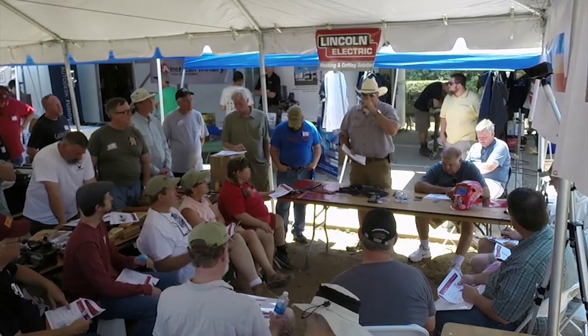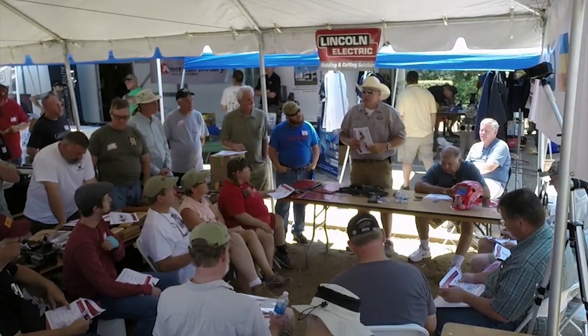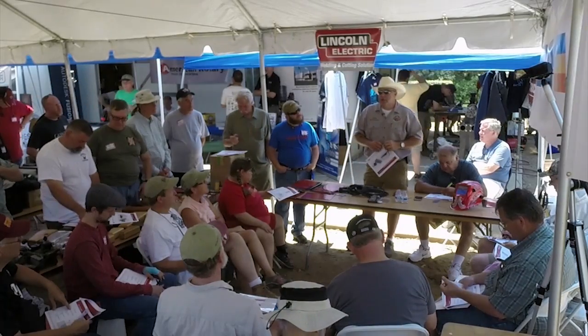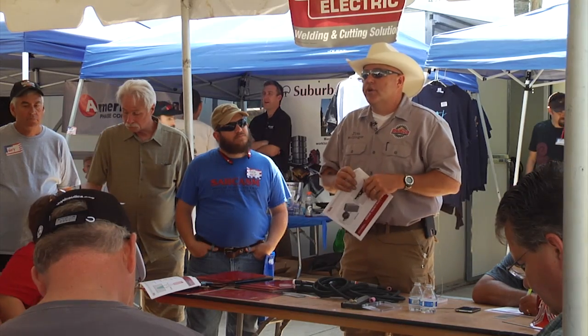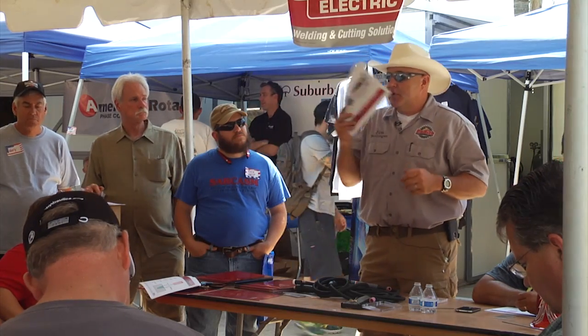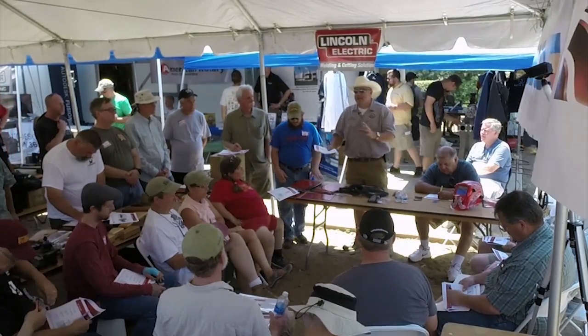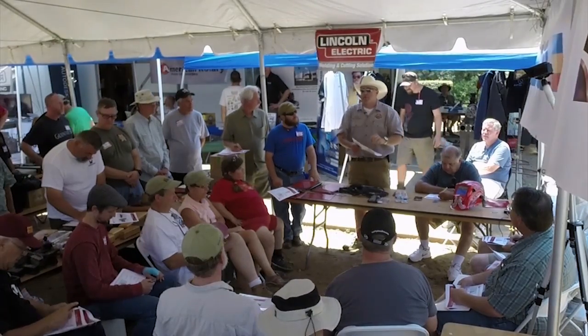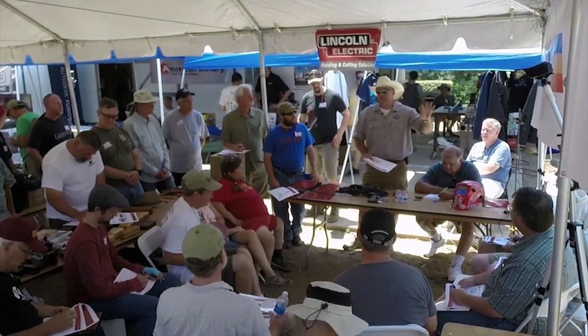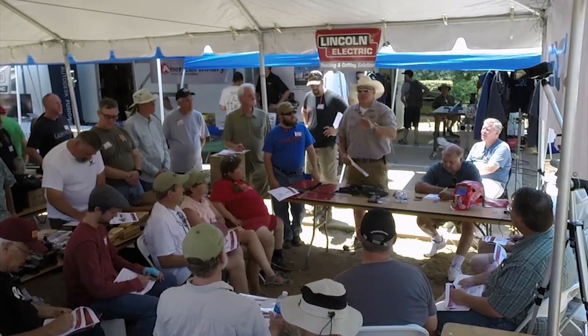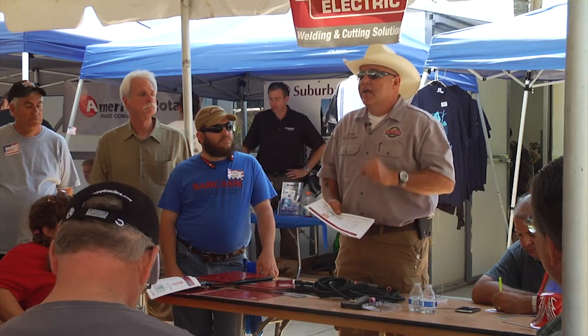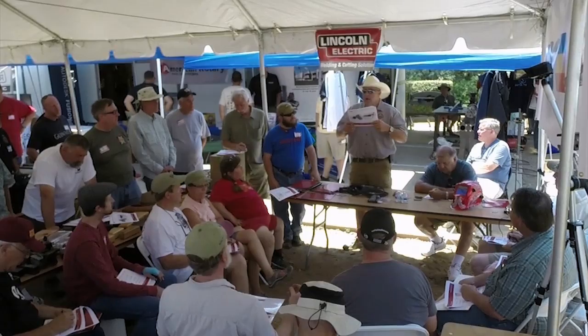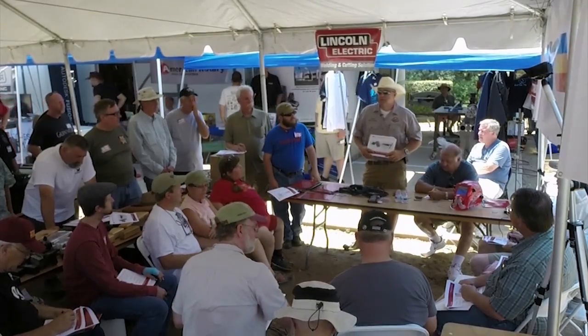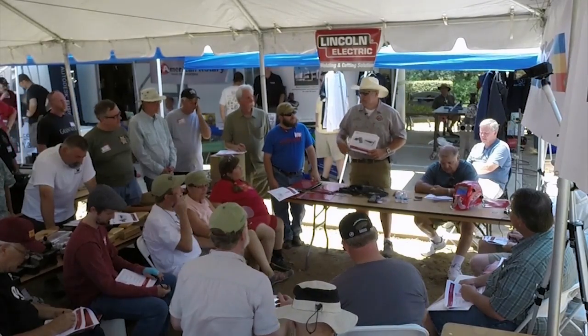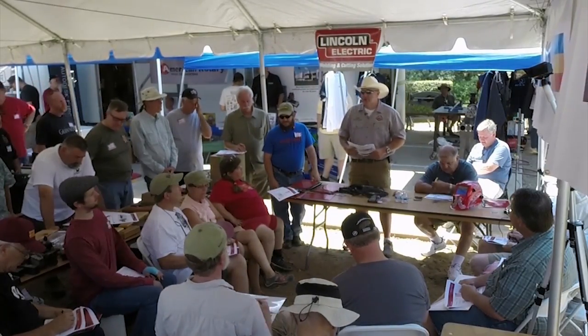Now, those of you that have pens and are taking notes, write this down. 6,280 degrees. At 6,280 degrees, tungsten melts, pure tungsten. I'm gonna tell you, for the sake of easy math, trust me, don't try to look it up on Google, because the decimal points are gonna mess you all up. The arc measured at the center is around 10,000 degrees. So if you have a 10,000 degree arc and 70% of the heat, how hot is the plate? 7,000 degrees. Right? 7,000 degrees.